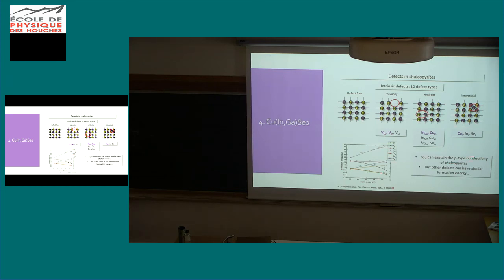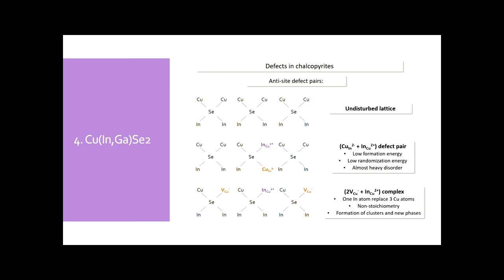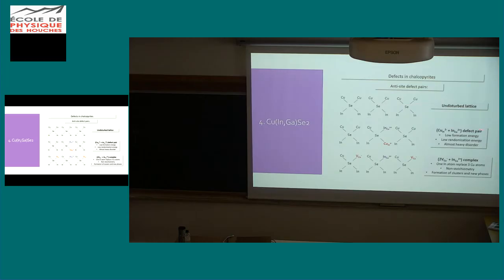Among all of them, copper vacancies used to be the most stable one, or the one that requires less energy to be formed, and can explain also the p-type conductivity of these materials. But this material is even more complex, and you can have different pair defects or complex defects. Like this is a non-disturbed lattice of CIGS, but if you change here indium by copper and copper by indium, then you have this kind of cluster that has low formation energy and can introduce disorder in the material.